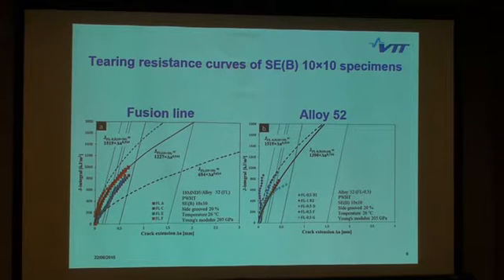Okay, so now on the alloy 52 side, so it would be on this side, the median curve has been fitted here. It follows the dark line, and the dashed line follows the curve that was measured for the single edge 10 times 10 specimens. And they seem to follow rather well, but there are some deviations. For example, for this one specimen, tearing resistance starts to deviate away from this behavior described by the line.